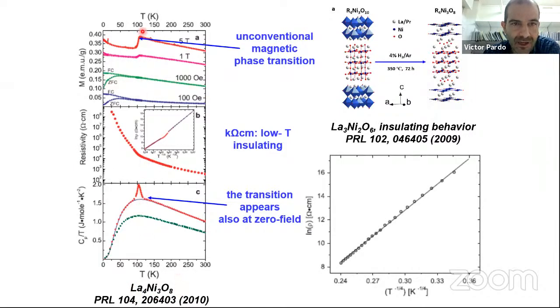a particular magnetic transition at about 100 Kelvin, pretty unconventional, that is also seen at zero field. So you see here in the specific heat, you see a cusp here at about 100 Kelvin. So something happens to lanthanum 4 nickel 3 oxygen 8 at about 100 Kelvin that is related to magnetism, but also maybe to structure.